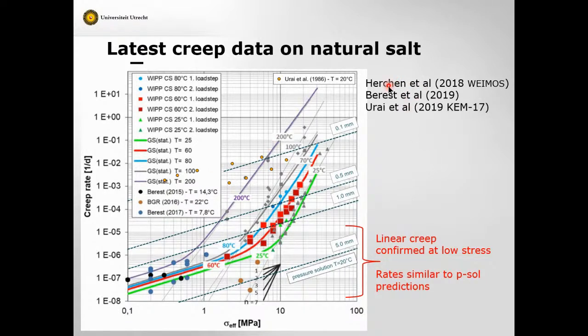And the very, very latest experimental data by people that I have enormous respect for. So a group at the IFG in Germany, Pierre Berest's group at the École des Mines and École Polytechnique, they have done creep experiments lasting years, and the results have just started to come out in 2019. And what do you see? Indeed, this is log creep rate a day against log of the applied stress. And what do you see?